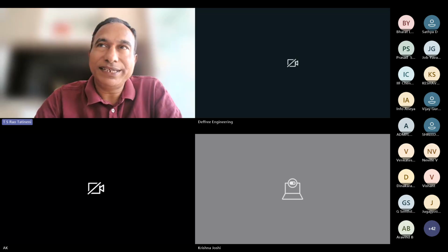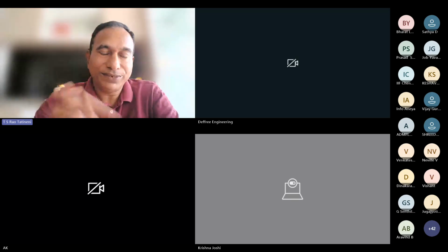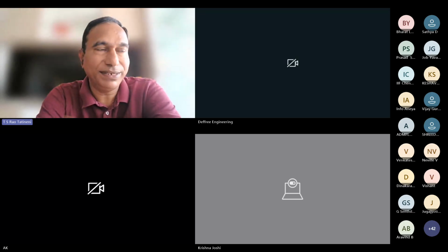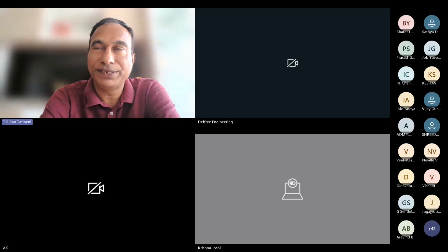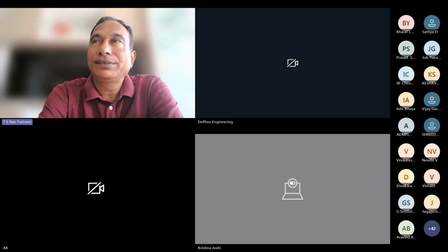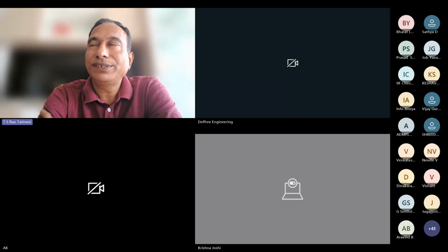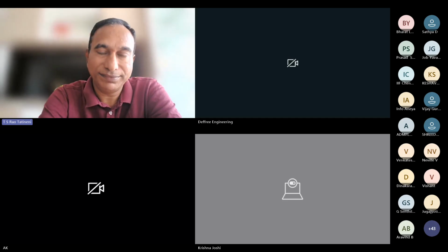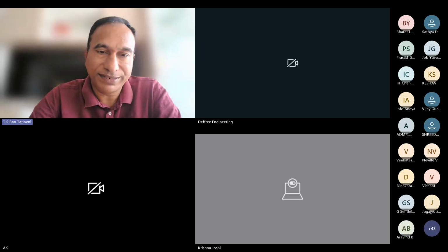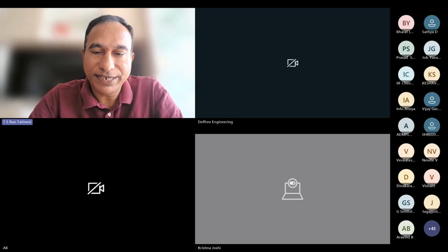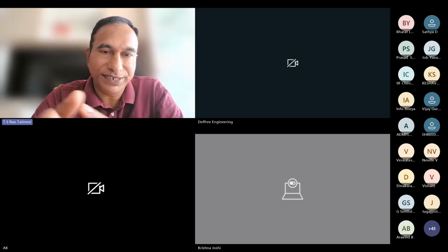But we need to study the gating. Without studying, it's difficult. But if you always follow the gating ratio, I don't see any problem. I think we need to study the gating. We need to see the filling pattern and cooling pattern as well. Cooling pattern is also very important. So what we do is we simulate and see whether directional solidification is happening and the cooling is happening as expected.